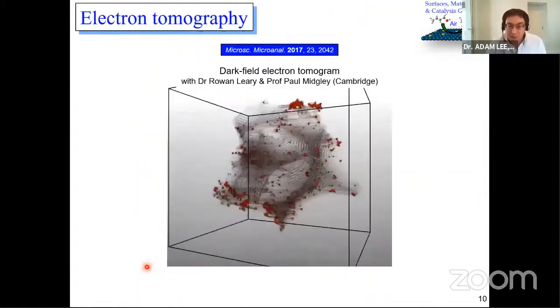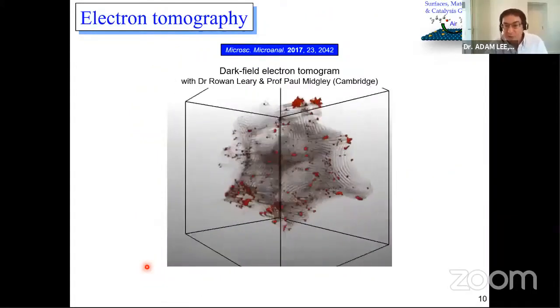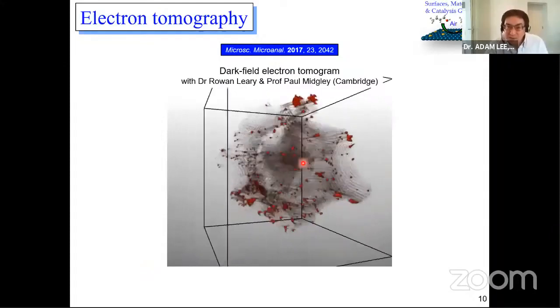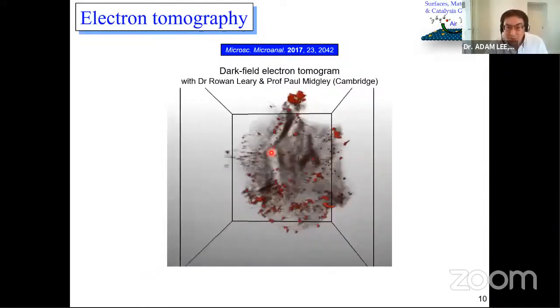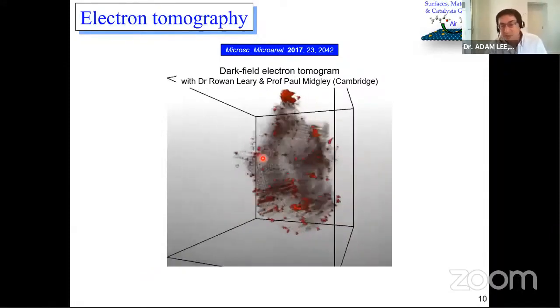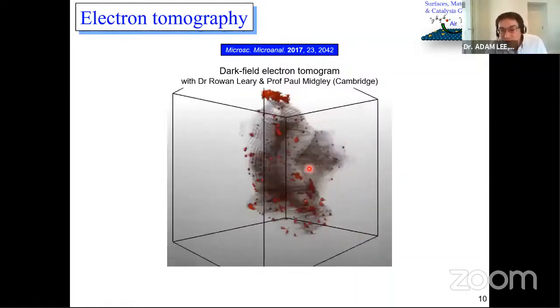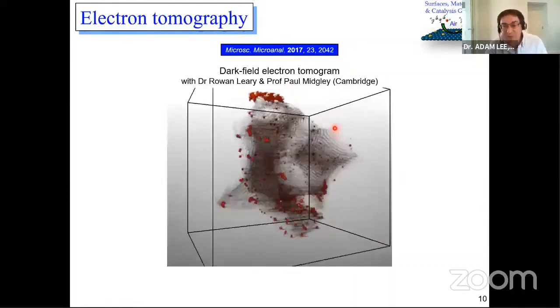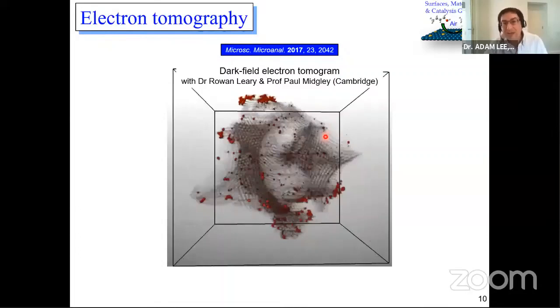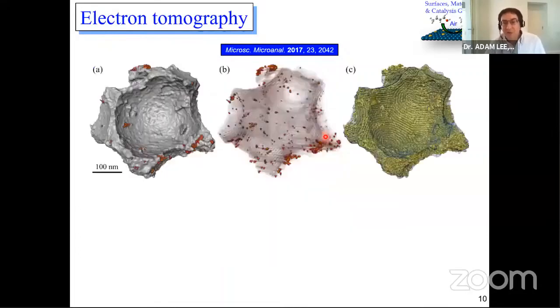Here is a tomogram showing you the separation. So what you can see here is some very large particles. These are the palladium nanoparticles, and they're only on the surface of the larger pores. And then there's some smaller dots that you can see. These are platinum nanoparticles, which are in the mesopores, the small pores. Easier to see here. So here we've got some rendering of those tomograms.